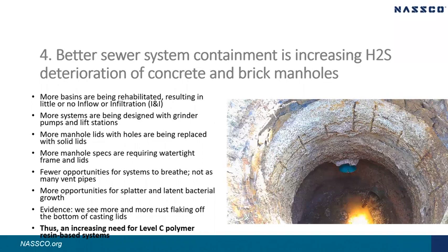My next point I'd like to make is better sewer system containment is actually contributing to increased corrosion of concrete and brick manholes. As more basins are rehabbed to prevent stormwater infiltration, there is less dilution of the sewage. More systems are built with grinder pumps and lift stations that can cause splatter. More lids with holes in them are being replaced with solid lids, and in many places, specifications are calling out for watertight bolt-down lids. These factors result in fewer opportunities for the system to breathe and more opportunities for latent bacterial growth that are the precursors to microbial-induced corrosion. We see this anecdotally when we flip lids and see aggressive amounts of rust flaking off the bottom of casting lids. The point I'd like to make is more and more manholes will require level C polymer resin-based solutions in the future.